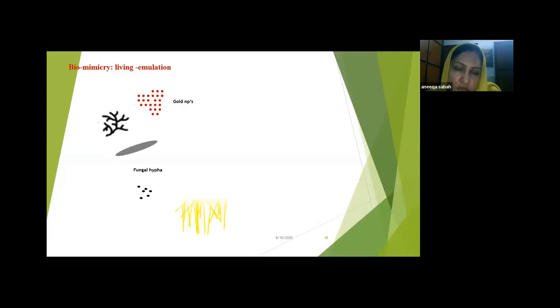It was done during my PhD, that biomimicry, living emulation. We have taken the concept of combination of natural material and our metal, the gold nanoparticles, and the fungi that grows on our bread and such. So we got this fungal hyphae and we mixed it with the gold nanoparticles. We grow them together, and after their growth, we got this kind of structure, that is the hyphae, and the metal nanoparticles are deposited on it, so we get the gold wires.